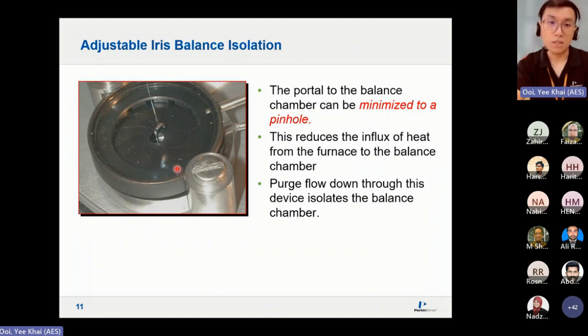So what's the purpose of this? When we do heating in TGA, we are doing high temperature analysis or there's a temperature decomposition. When the sample decomposes, it becomes gas and goes up into your balance if there is no purge gas, because it's now lighter, with lower density, it tends to go up. So this will block off the gas coming out from your sample chamber going into the balance and contaminating your balance. It also reduces the influx of heat from the furnace to the balance chamber, so the heat will not go into your balance and cause expansion of the balance as well.